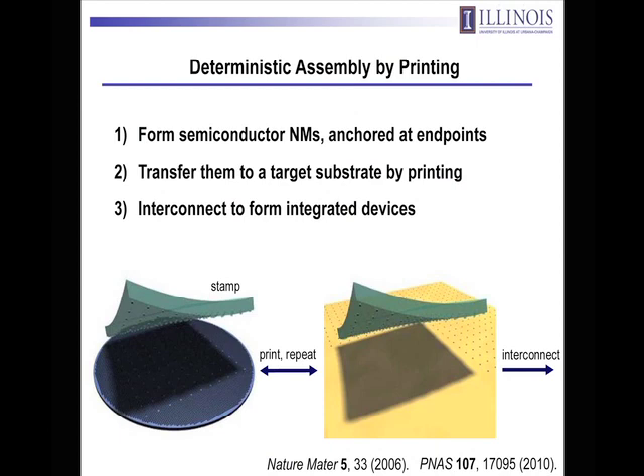but still allowing these nanomembranes to be exploited in the ways that I've suggested previously. In this scheme, we're using ideas adapted from the world of soft lithography, where instead of printing molecules, we print solid inks, the inks being the nanomembranes themselves. And we do that in a way that exploits the known positions of these elements on the wafer because we're defining them lithographically. So we create them in a way that doesn't simply allow them to float off of the wafer after they're completely undercut etched. Instead, they're tethered to the mother wafer at strategic locations such that you can come in with a soft elastomeric stamp and contact those undercut etched nanomembranes. Van der Waals forces can be sufficiently strong that when you peel the stamp back, you pop the anchors, thereby inking up the stamp with those nanomembranes.